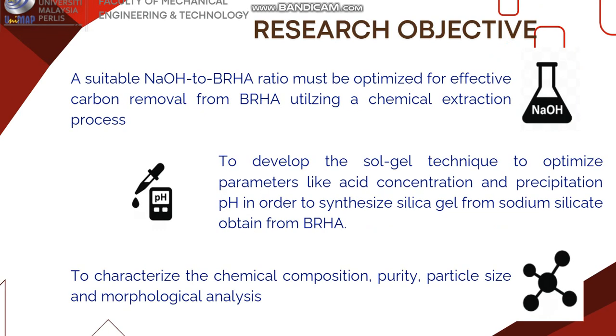The main objectives of our research are, first, to determine the optimal sodium hydroxide to BRHA ratio for effective carbon removal. Second, to develop the sol gel technique, optimizing parameters such as acid concentration and pH for silica synthesis. Thirdly, to characterize the extracted silica in terms of composition, purity, morphology, and particle size.